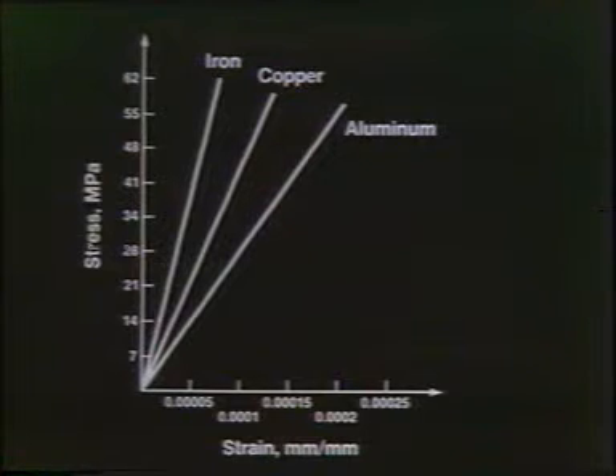We have looked now at what we can get for a material, a piece of steel, a piece of copper. We have got these characteristic pictures that we can develop. But how do they compare? That is, if we're interested in looking at one metal versus another. Now obviously, the kind of plot that we have in this particular slide, which is an indication of the elastic portion of the stress-strain curves for iron, copper, and aluminum. And those particular curves, this being for iron, says it has a modulus of elasticity that's higher than copper. This being copper, which has one higher than aluminum, that being the aluminum.